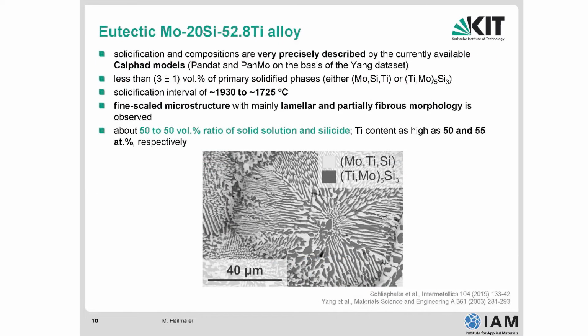Okay. So here in a larger magnification, the fine-scaled eutectic microstructure. This is the alloy composition. Those of you who have looked carefully would see all of a sudden, this is in atomic percent, all the concentrations I give are in atomic percent. If you would now calculate the molybdenum content, you would say, this is only about 30% molybdenum. Is this still considered a molybdenum alloy, or is it rather already a titanium alloy? In terms of atomic numbers, it's a titanium alloy. In terms of weight, if I would calculate weight percent, it would be still a molybdenum alloy. And since we are doing casting, all the metallurgical engineers talk in weight percent and not in atomic percent. So we can still say this is a molybdenum-based alloy.